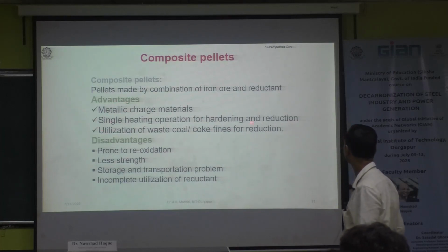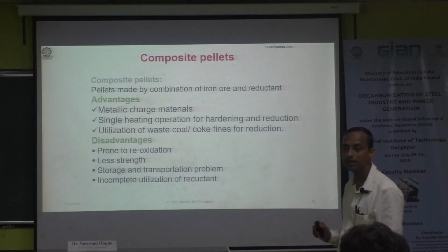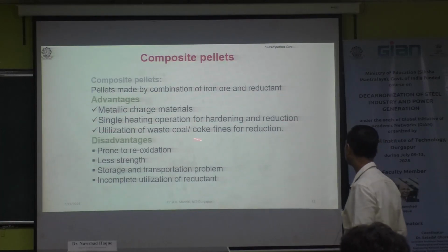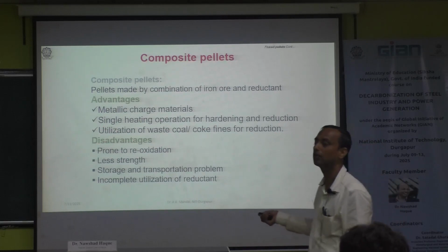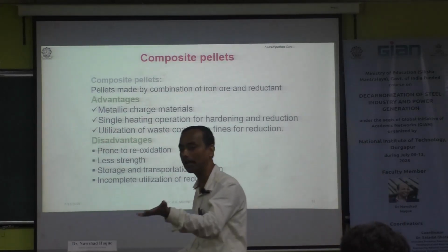Single heating operation for hardening and reduction, no separate heating operation. Utilization of waste fines as a reductant. But the disadvantage is that it is prone to reoxidation. This composite pellet means one type of DRI.